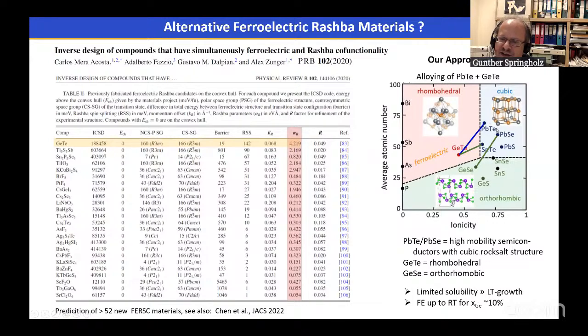and hope to retain the good semiconducting properties of lead telluride, which exhibits very high electron and hole mobility at low temperatures, and induce ferroelectricity by introducing germanium atoms, very similar to the approach to produce a ferromagnetic semiconductor by taking gallium arsenide as a semiconductor host material and adding manganese to the system.